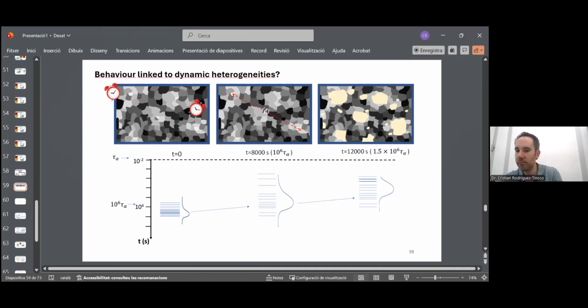Then if you continue doing this annealing, more and more regions will become liquid, and eventually the whole system is transforming into the liquid. So this is the important thing that we can observe with ultrastable glasses, that we somehow are able to measure a kind of dynamic correlation length. It's not exactly the dynamic correlation length we have in the supercooled liquids, but it gives us some idea of the separation between the regions that have similar relaxation times in the glass.